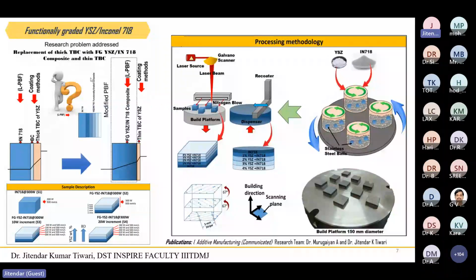Okay, but we had tried with the powder bed fusion, because in case of powder bed fusion, the melting happens in a very small region. If you talk about the melt pool size in case of the LPBF process, it's around, I would say, 100 micron or 150 micron. So there the problem of agglomeration is always there. But here we can avoid these kinds of problems, because everything is in moving condition. So some bounce back phenomena can happen, and your reinforcement could not be properly distributed inside the matrix material. So these kinds of problems are associated with the LDED process.